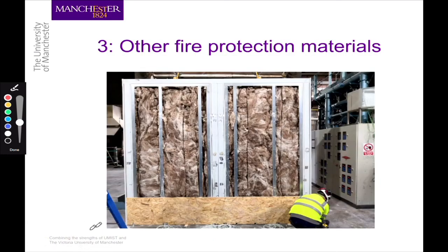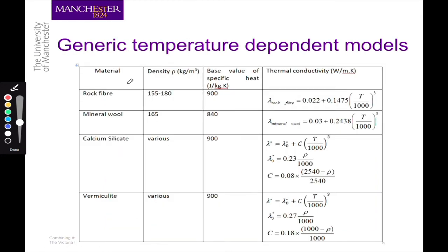Finally, about other fire protection materials, it is really difficult to find a lot of detailed research on these materials, for example, mineral wool. But a few years ago, I searched the internet and a lot of literature as well, and came up with quite a good set of results for various materials. And I did systematic research, and I found that it is possible to provide a number of temperature-dependent models for thermal conductivity of the various materials. It is thermal conductivity which is most important, because these materials are lightweight and their specific heat values don't affect results that much.